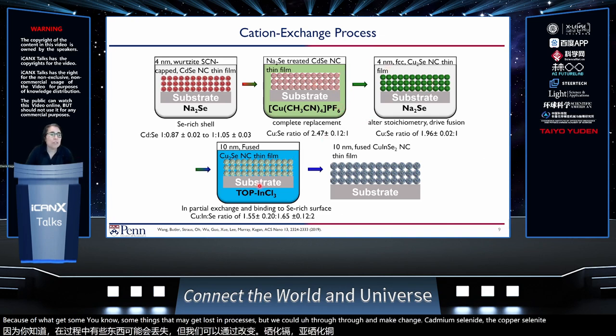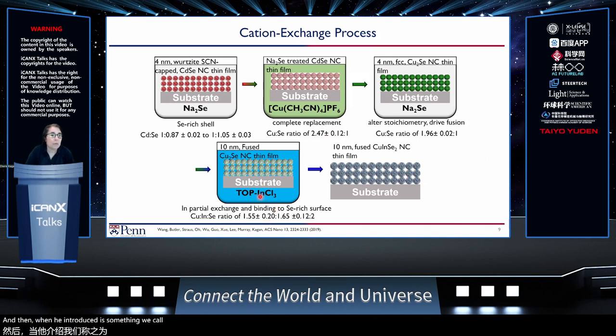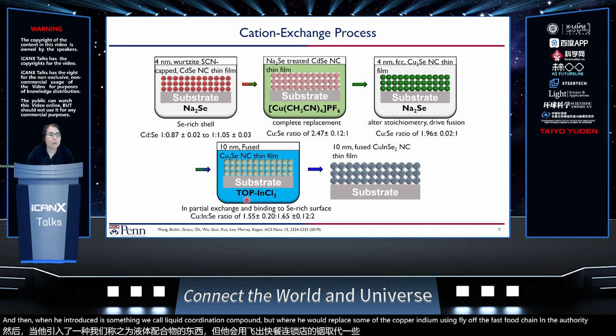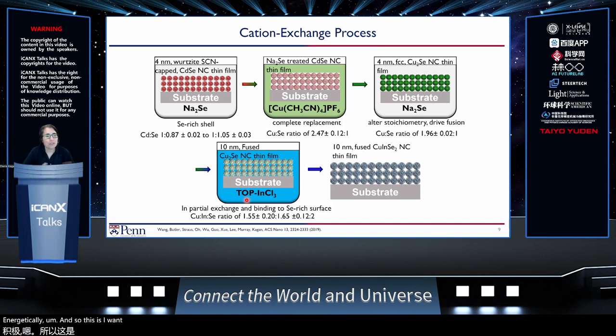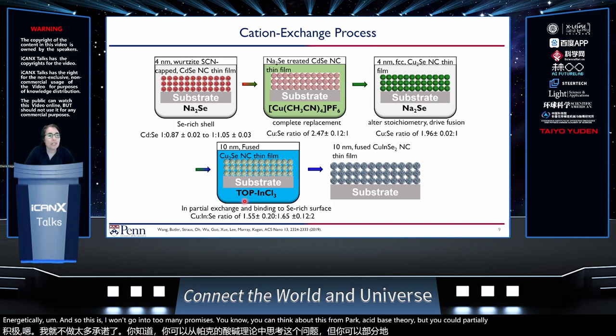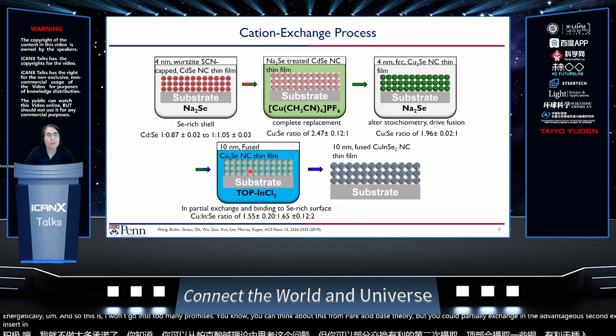And then what he introduced is something we call a liquid coordination compound, where we would replace some of the copper with indium using trioctyl phosphine indium chloride. And so it's advantageous energetically. I won't go into it, but for any chemist aficionados, you can think about this from hard acid base theory. You could partially exchange, and it would be favorable to extract some of the copper and insert indium into the material.